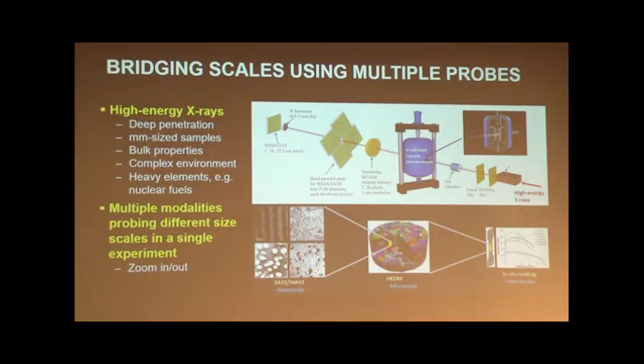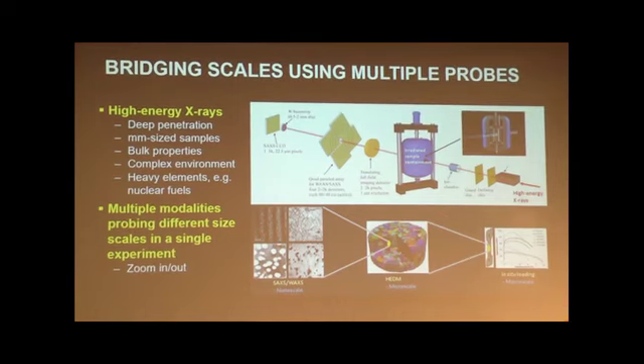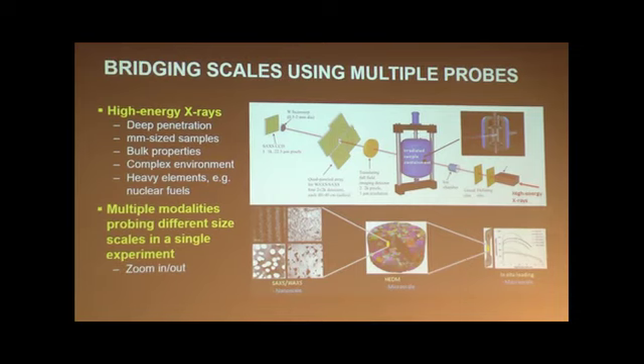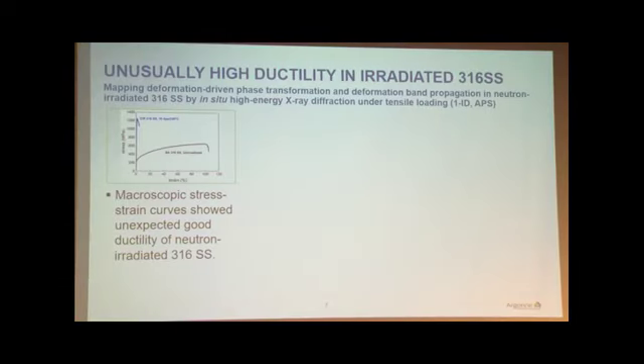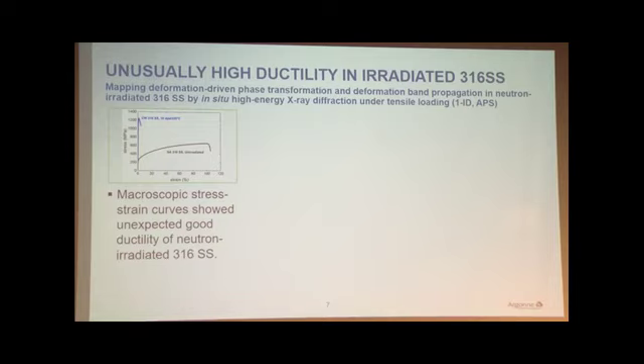And also going to mesoscale, you can look at individual grain or subgrain and see what happened there. In one single experiment, you can get information from nanoscale to mesoscale and also up to macroscale to directly link all these microstructure features to the material's property, which was unthinkable before. So this is an important capability that's enabled by high-energy X-ray. I'll just give you a few examples of what we can learn from this kind of experiment.